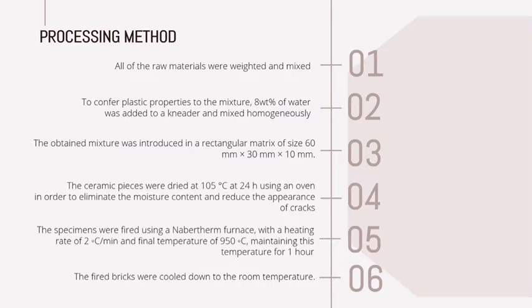All of the raw materials were weighed and mixed. To provide plastic properties to the mixture, 8% of water was added in the kneader and mixed homogeneously. The obtained mixture was introduced into a rectangular mould of size 60 mm by 30 mm by 10 mm. The ceramic pieces were dried at 105 degrees Celsius for 24 hours in an oven in order to eliminate the moisture content and reduce the appearance of cracks.